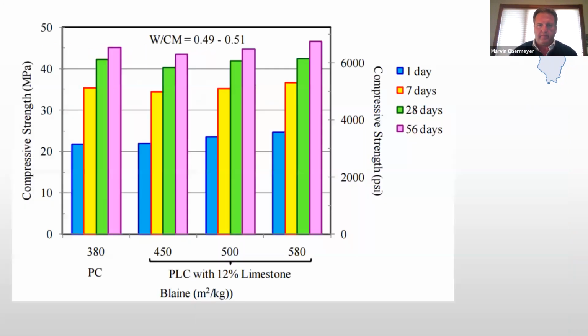Well, that's what we're talking about here. In the first set of charts, Portland cement is 380 Blaine, in square meters per kilogram. So that's the surface area of that cement on that day for that run. You can see the 1-day, the 7-day, and the 28-day. The 28 days are the green bars, and the water-cement ratios are basically the same for all of these.